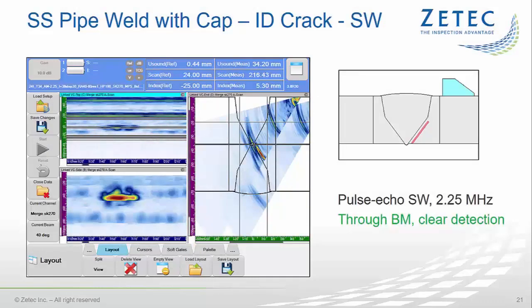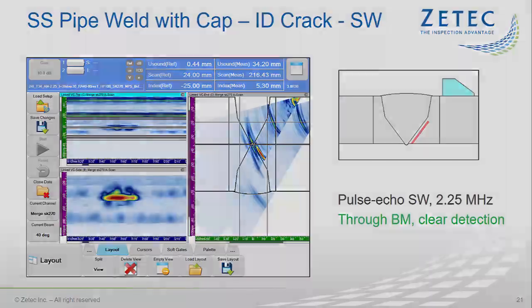Let's look at shear wave examination data first. This slide shows merged data from 40 to 70 degree beams obtained with the standard Zetec AM 2.25 MHz probe in pulse echo mode. The crack is on the near side of the weld, so the acoustic beam is passing through relatively fine-grained base material, and we get a clear detection of the crack with potentially very accurate length sizing. We cannot observe any clear tip signals for through-wall sizing.